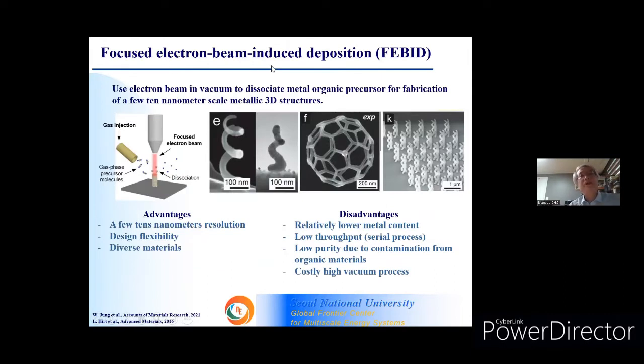Focused electron beam induced deposition uses electron beam in vacuum to dissociate metal organic precursor for fabrication of few 10 nanometer scale three-dimensional structures. However, it has disadvantages: low throughput since this is a serial process, low purity, and high cost due to the need for a high vacuum process.